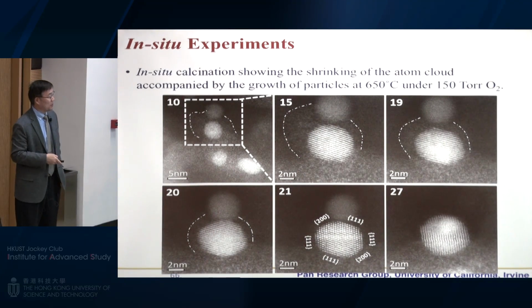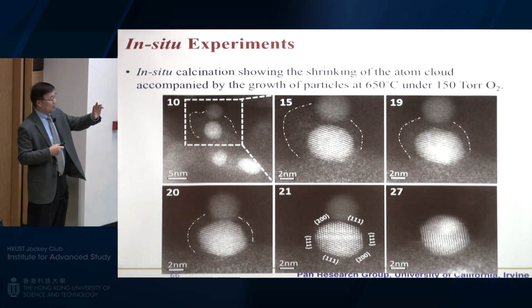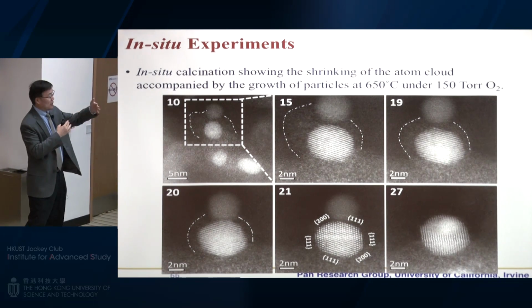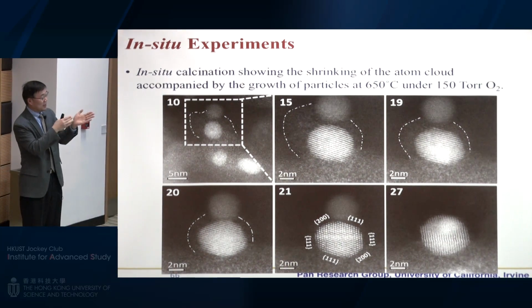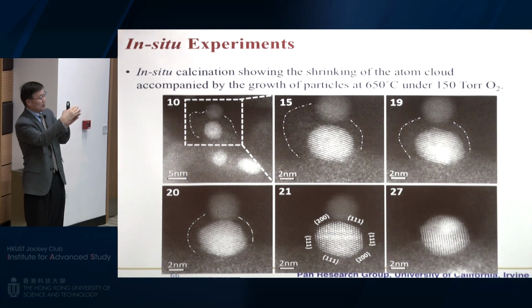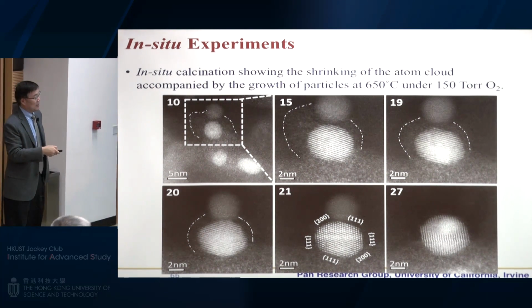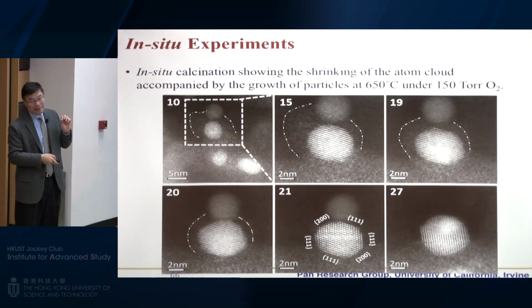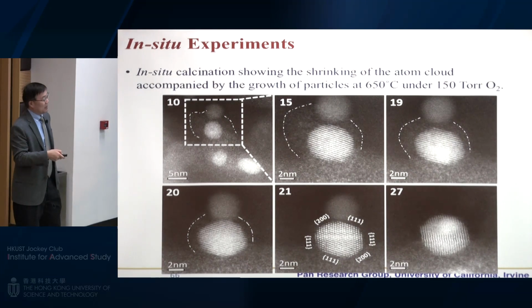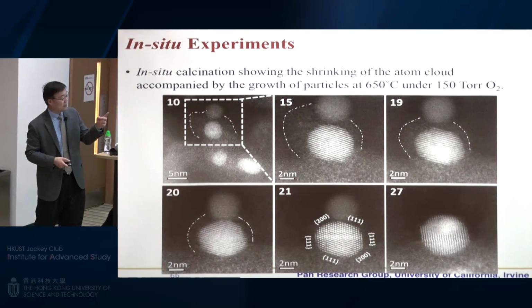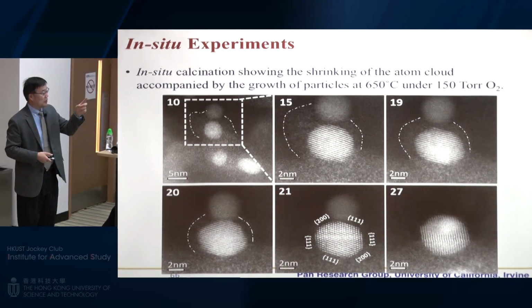In this small example, you can see the particle rotation. If you are interested in the transition from two particles to one particle and the surface energy, like a crystallographer studying different special grain boundaries, the particle will rotate and have a very nice match at the boundary, and then suddenly the particles just merge and become one. This process is too fast to be seen by STEM. The scanning mode is very slow. Now we have a direct electron detector, the K2 IS camera, recording 1,500 images per second.